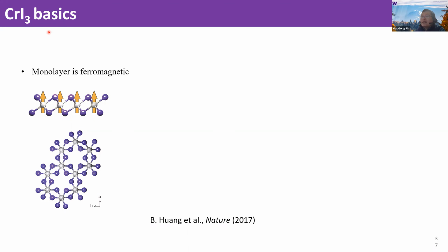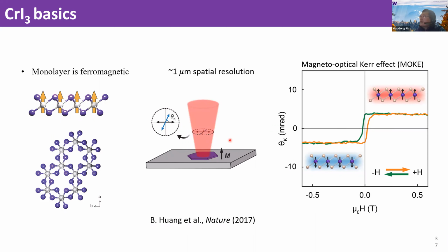The system we use is CrI3, which my group is the most familiar with. Here is a brief introduction of chromium triiodide. In a monolayer, if you look from the top, the chromium atoms form a hexagonal lattice, and they form edge-sharing octahedral structures with the iodine atoms. The spin is out of plane. Several years ago, my group performed magneto-optical Kerr rotation measurements. We sent linearly polarized light on a sample and looked at the polarization rotation of the reflected light, which we call the Kerr angle, theta K. Measuring this Kerr angle as a function of magnetic field in the monolayer, we observe a very clear hysteresis curve. This is the hallmark of ferromagnetism with out-of-plane magnetization in the monolayer.